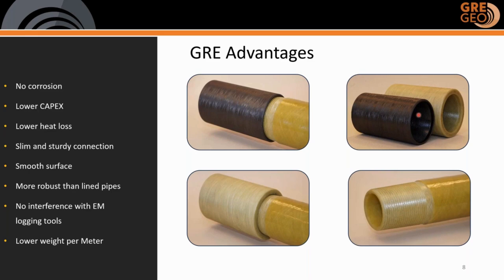Xavier, one thing I would like to add is that FPI, the supplier of the pipe, have developed a combined coupling, which from inside is made out of GRE material, and outside the compressive and hoop strength is given by carbon fibers. As you see in the picture, in comparison with the pure GRE coupling, the OD of the combined coupling has become significantly smaller. It is not directly comparable with steel, but we could at least considerably reduce the excessive OD of the couplings. I think that answers the question pretty well.